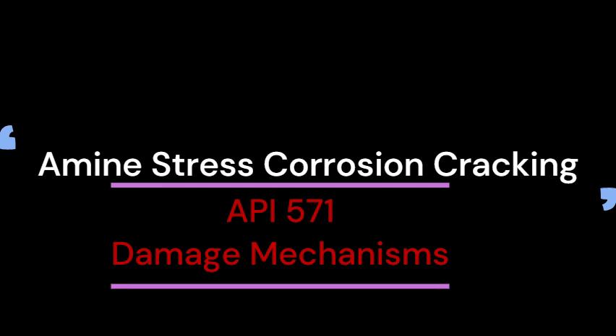Okay, so where then? They tend to pop up in the zone of highest residual stress, which is actually just outside the visible HAZ, maybe a tenth of an inch or more away, a few millimeters, that band just beyond the metallurgical change from welding. That's fascinating. The highest risk isn't where the metal changed, but where the stress gradient peaks just beyond it.